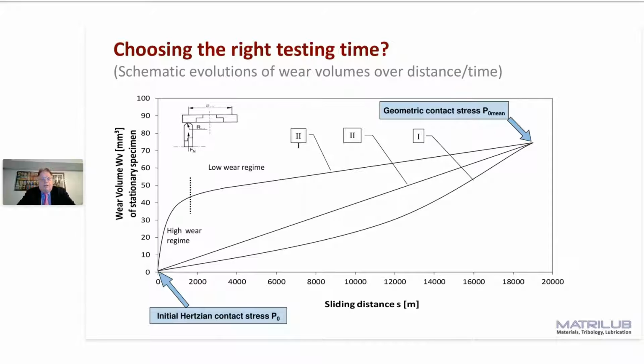You have 3 evolutions in the wear. You have one evolution which goes straight. You have another one which starts slowly and accelerates. You have one with a high running-in wear. You reach the critical contact stress, and then you come into a low wear regime.